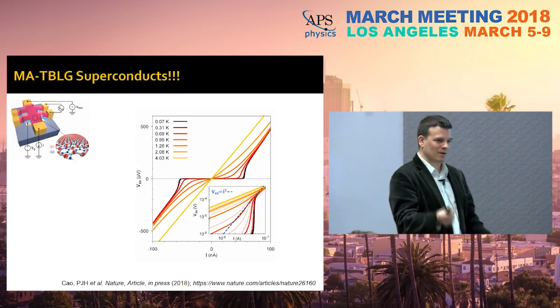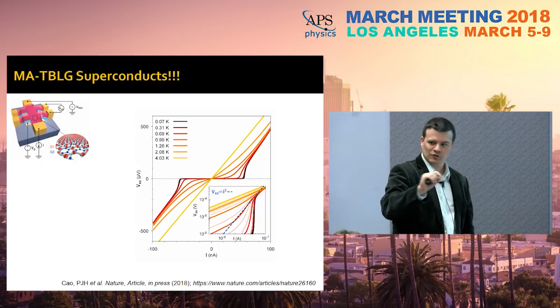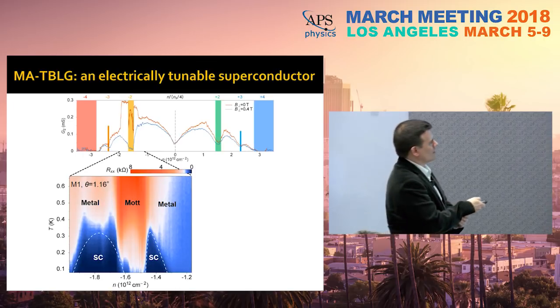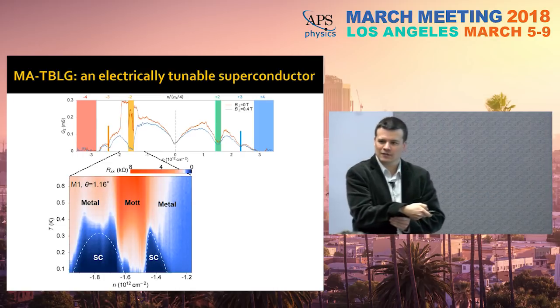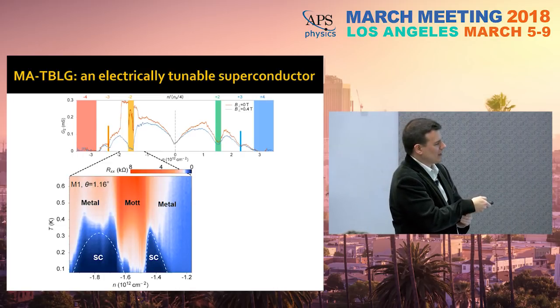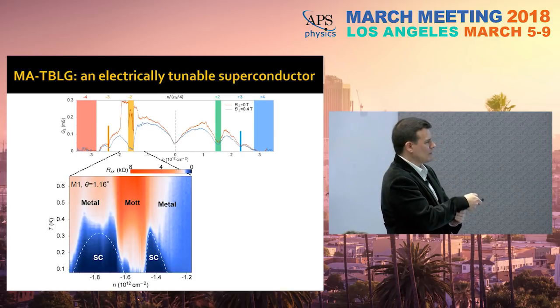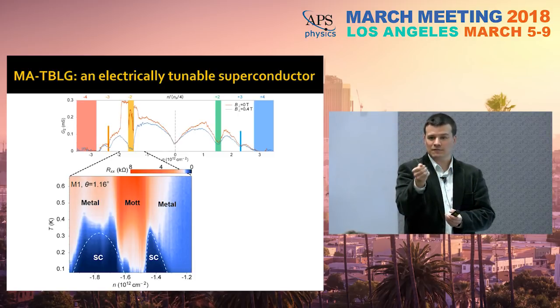Now, the nice thing, remember, is that we have this gate voltage control with which we can continuously tune the density in our system. So when we zoom in around this area, this is what you see. This is the resistance as a function of temperature and density. Red means high resistance, dark blue means zero resistance. This is the half filling, this Mott-like insulator state. If we dope with a few electrons, we have an electron-doped superconducting dome. If we dope with a few holes, we have a hole-doped superconducting dome. And we can do this continuously as a function of gate voltage in a single device, okay?